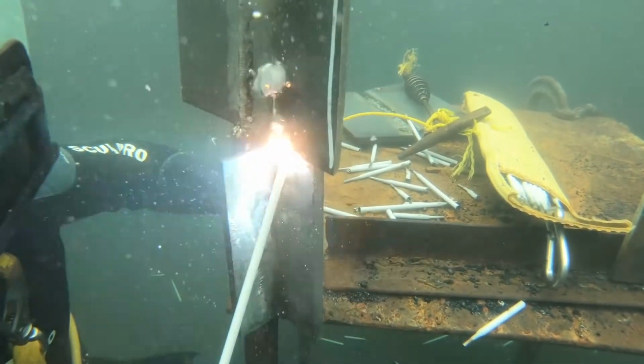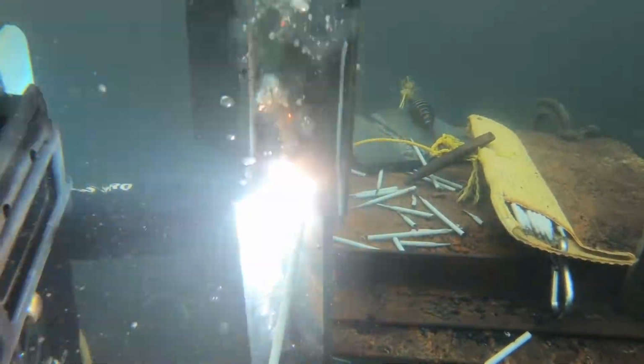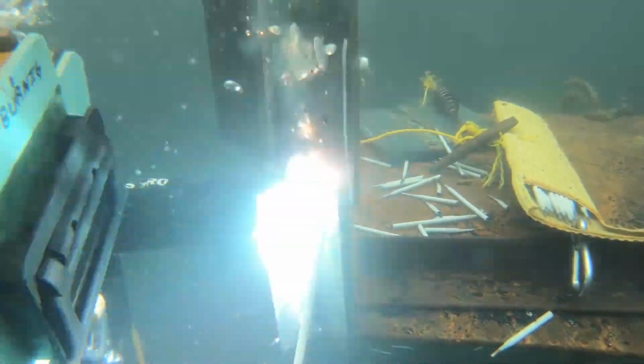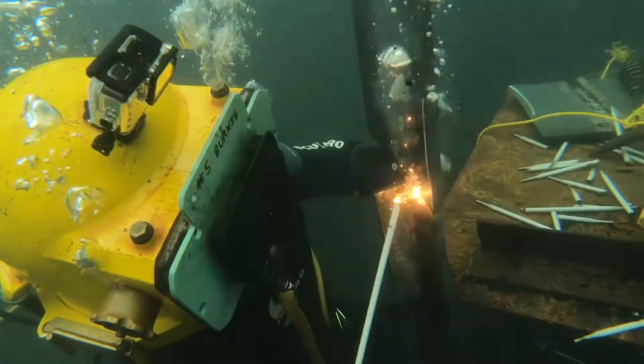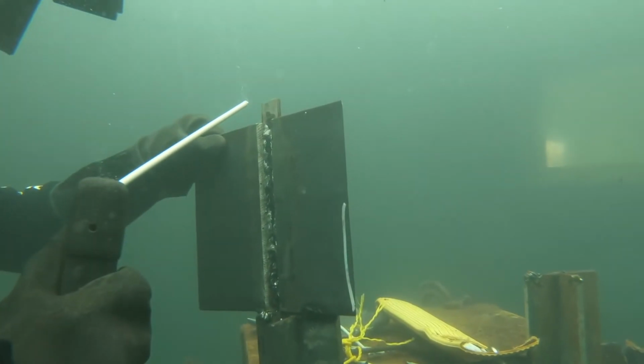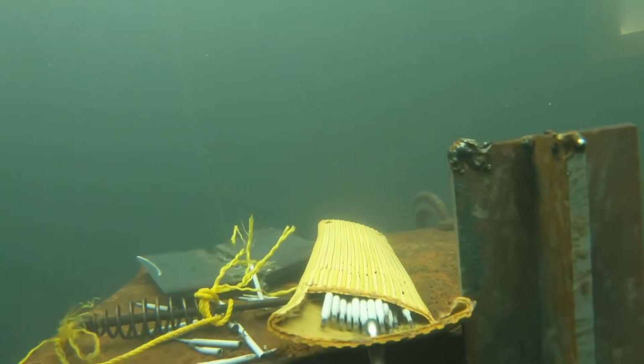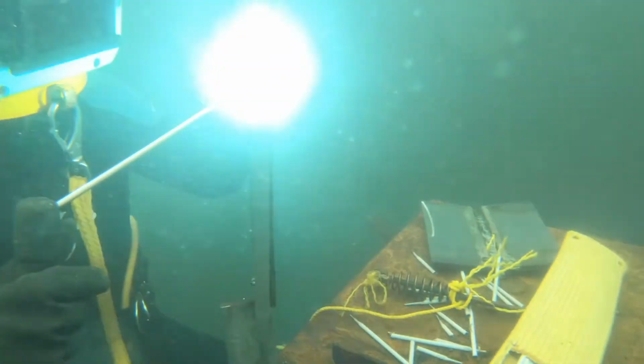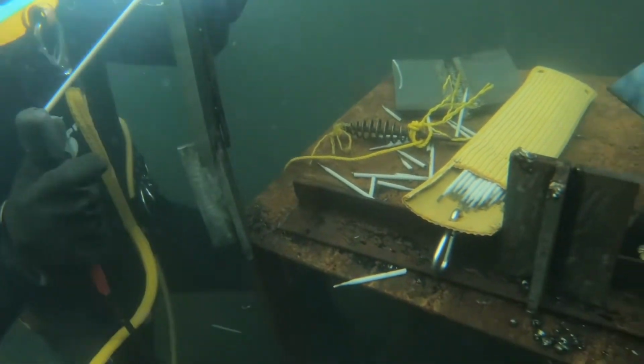Having to re-tack up that plate, kind of knocked it off, didn't tack it too well the first time. Coming in on the second fill pass. Like I said, it's more of a drag. When you're running 70-18, you're about an 1/8 inch, kind of floating off of the plate just a little bit. When you're doing your underwater, you have to keep that contact so the arc will stay established. So it's a little bit different. If you push too much, you're just going to start gouging out that plate.